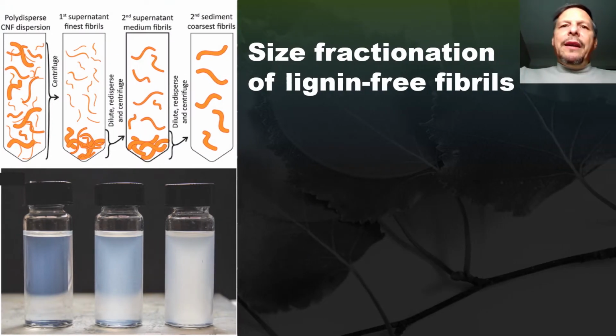And one interesting component here that is actually of recent data is the separation of microcelluloses in different lateral fibril size. And by using simply centrifugation, maybe you can think of different other techniques for fractionating fibrils by size, we can then obtain different populations of fiber width or diameter, from the finer ones on the left to the coarser ones on the far right. So here we have lignin-free fibers, bleached fibers. In this particular case, a very high level of fibrillation or deconstruction. We can think about this as cellulose nanofibrils or microfibrils.